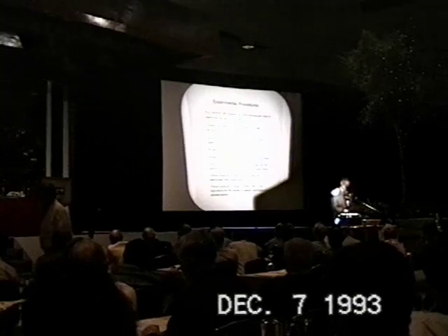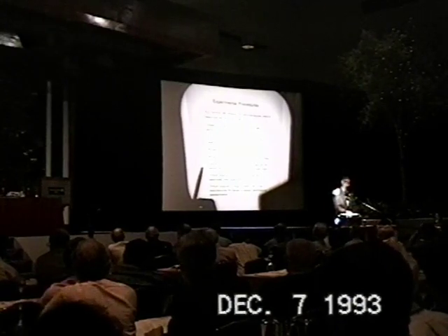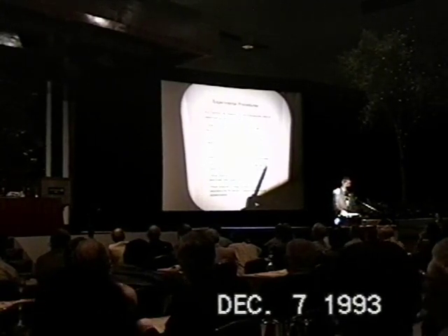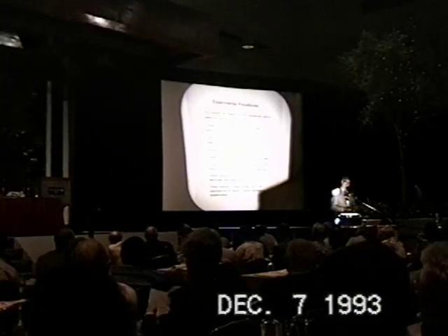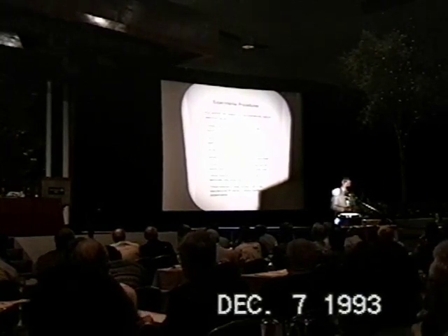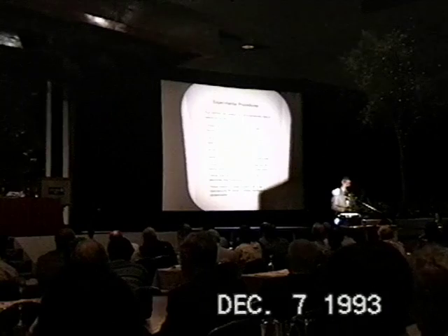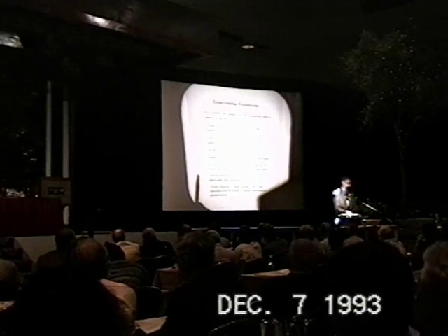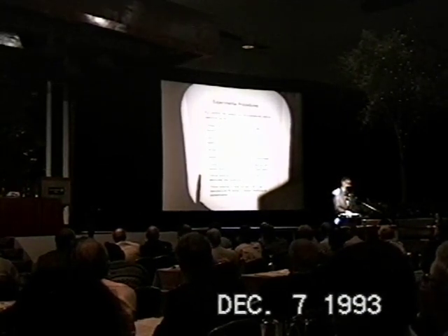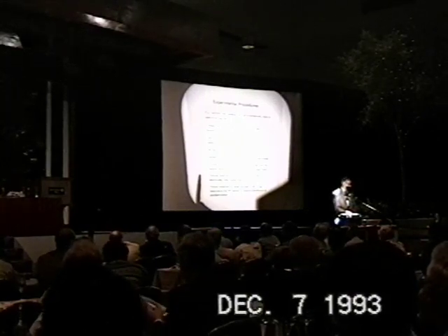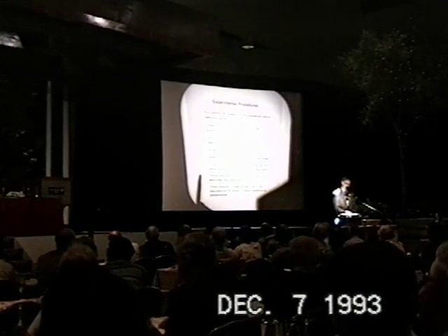We used cyclic loading and unloading to attain deuterium to palladium as well as hydrogen to palladium ratios very close to 1. That means essentially 1 plus or minus 0.05, which is incidentally the accuracy of our technique. Tritium analysis was performed on the electrolyte, the deuterium fill gas in the headspace of the cell, and the palladium pieces adjacent to the electrodes before an experiment.